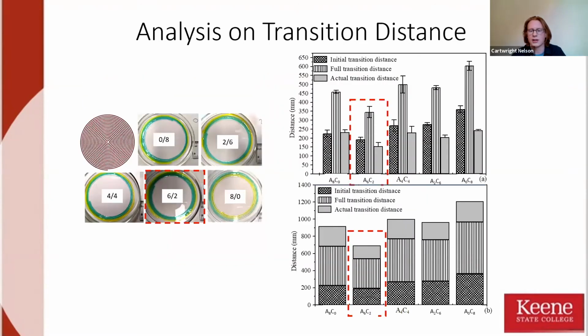And okay, so the 6-2 combination of alginate and CMC is shown here as having the lowest initial full and actual transition distance, which again is that difference. So this is very good, and the reason that it was that one and not 8-0 that had the best transition is most likely because 8-0 wasn't viscous enough and actually mixed more within the transition chamber, which took longer for it to switch from one to another because it mixed so much, whereas the slightly more viscous 6-2 was able to switch from one material to the other without mixing as much.